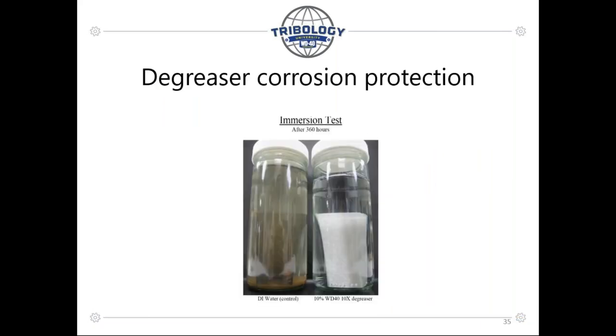And so what I'm showing here is an immersion test after 360 hours. And the jars have the same type of steel panel in it. The jar on the left is filled with DI water, and you can see that rust is starting to occur there. And on the right is the same panel, just soaked in our degreaser.